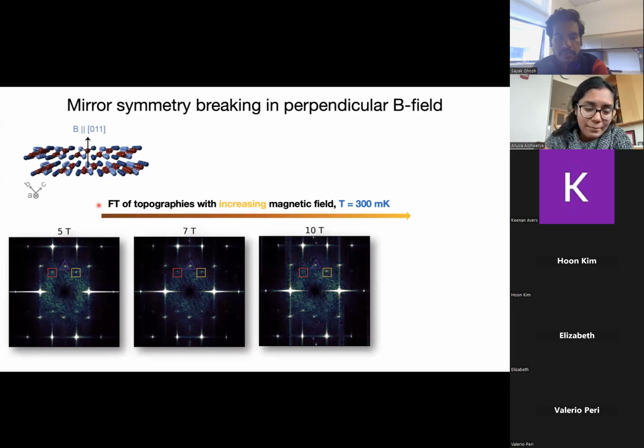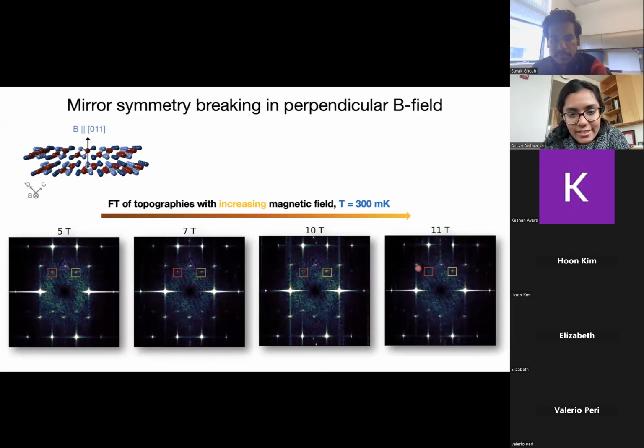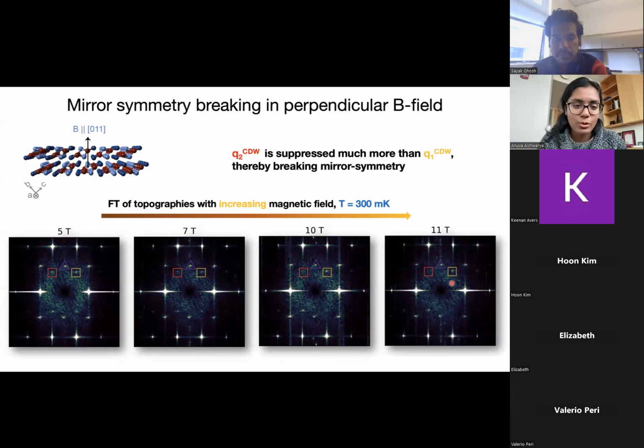By 10, we see something strange happening. You can see that the CDW in the red square is pretty weak compared to the other two. And at 11 Tesla, it's at the same level as the noise level, so it becomes undetectable. Now, as I said before, the red and the yellow are related by mirror symmetry. So we see that in the presence of a magnetic field, the CDW is breaking mirror symmetry.